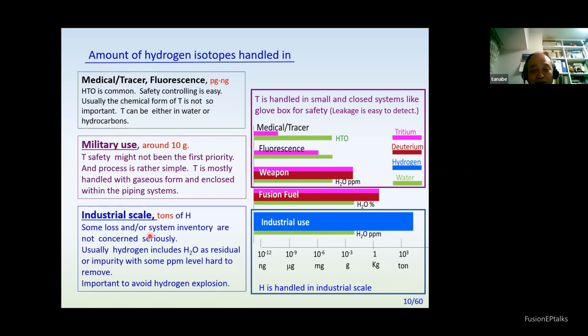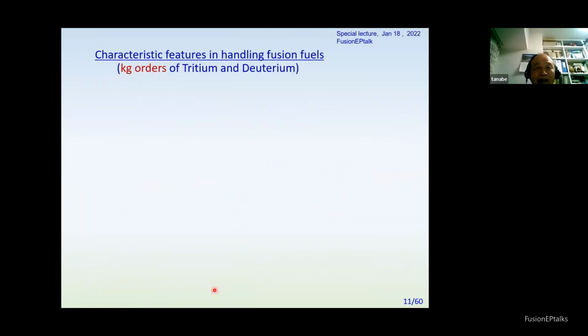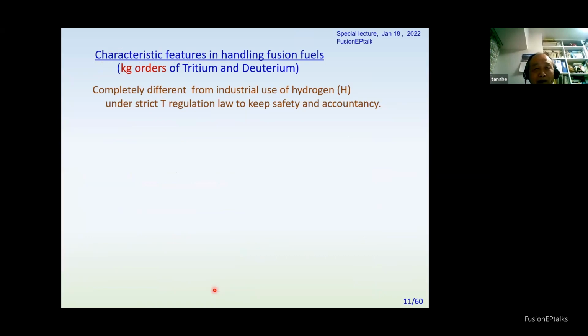Okay, industry use is quite totally different because they are using tons of hydrogen and they don't mind some losses from the systems. Water, as I told you later, is quite an important impurity in fusion systems, but at industrial scale they don't mind. Some water is acceptable. Of course, hydrogen explosion is very important, so they should avoid it. To compare, in a fusion reactor we are using kilograms of tritium and deuterium simultaneously. So this system is completely different from industrial use of hydrogen, with a strict tritium regulation law to keep safety and tritium accountancy.